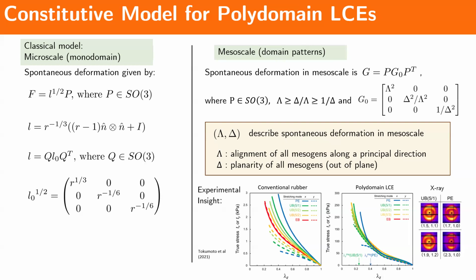What that means is that in the polydomain LCE, you have a mechanism to negate in-plane shear stress. The two principal stresses are the same, so basically there is no shear stress. They also looked at this material with X-ray imaging and saw indeed that there is an evolution in the mesogens of these materials that negates the in-plane shear stress. So, from these experimental insights, we postulate that these two variables, lambda and delta,